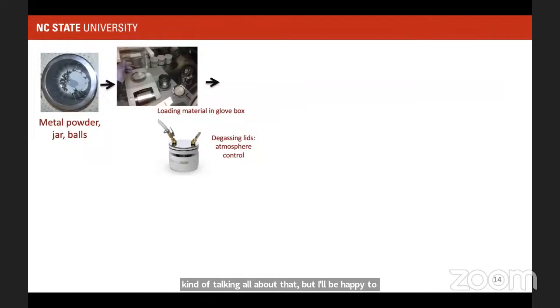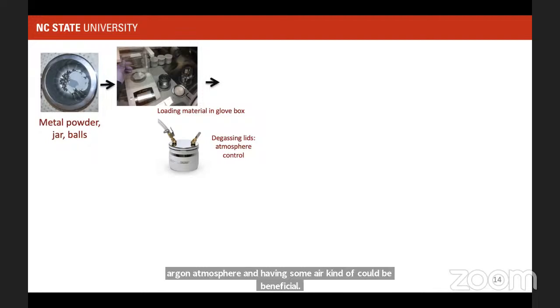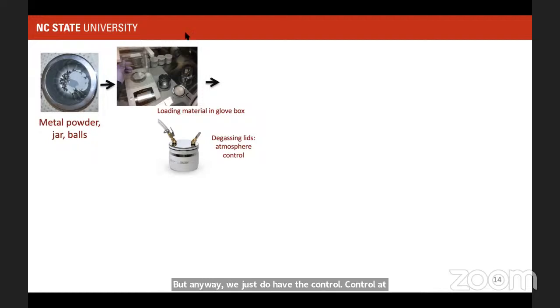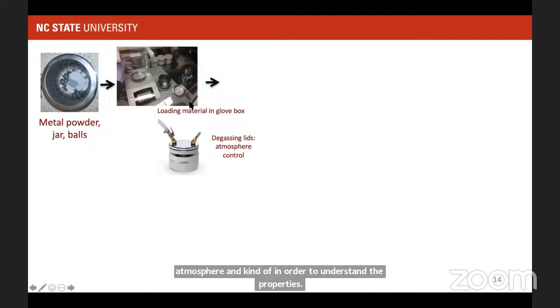So to make the solid solution, we know there could be different techniques. One could be ball milling, mechanical alloying, where we put huge energy in and can make a non-equilibrium supersaturated solid solution. With that hope, we took these metal powders, put them in a jar, and sealed them in a glove box in a high purity argon atmosphere. Later we learned that you really don't need high purity argon, and having some air could even be beneficial. But anyway, to have a controlled atmosphere and to understand the properties very well, we do all the processing in high purity environments.